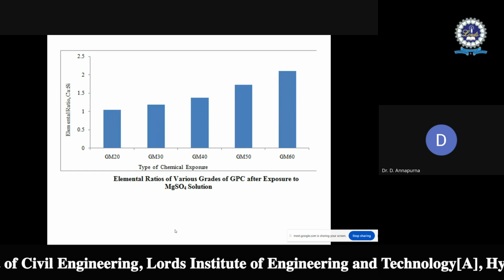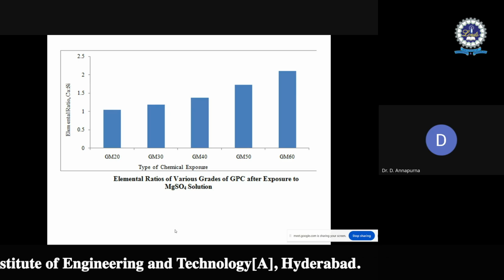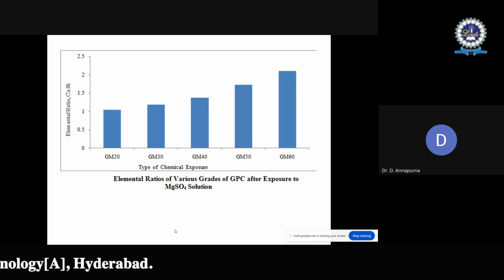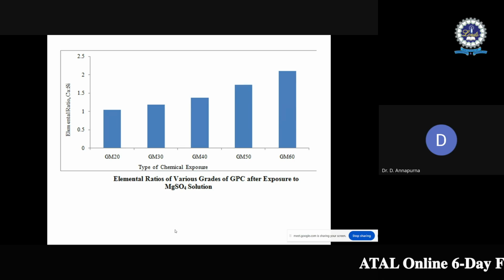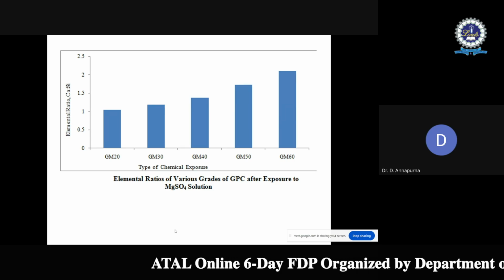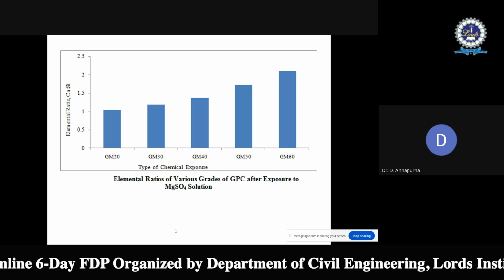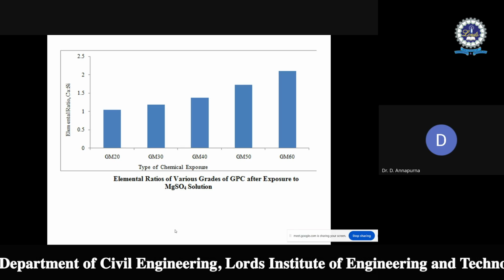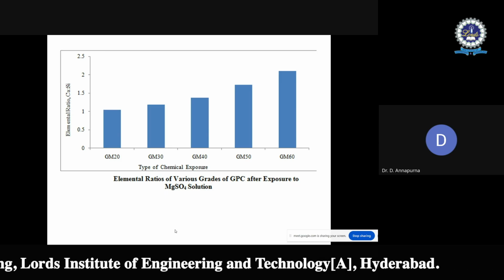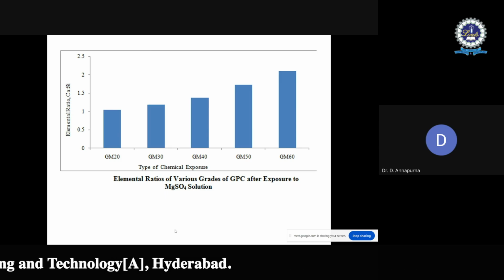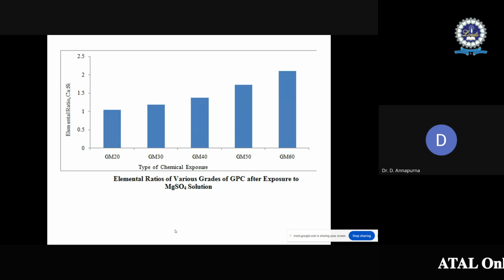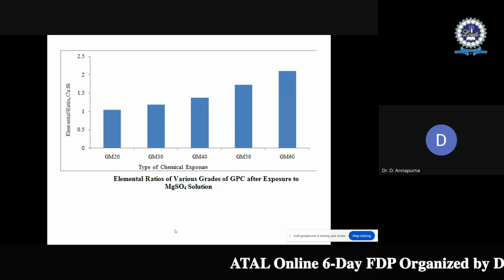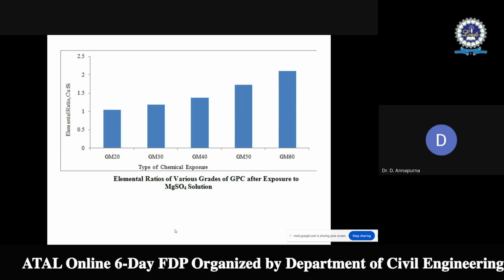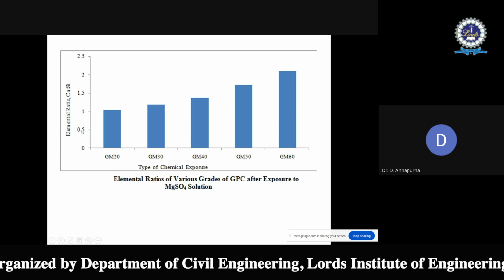If we look here, it is seen from the earlier slides that as GGBS is increased in the production of geopolymer concrete, calcium aluminate silicate hydrate gel is propagated in the geopolymer, right? Then if we look at the same phenomenon, this calcium rich material is reacting with the sulfates and influencing the calcium silicate hydrate gel, right? So that can be seen through this calcium by silicate ratio.